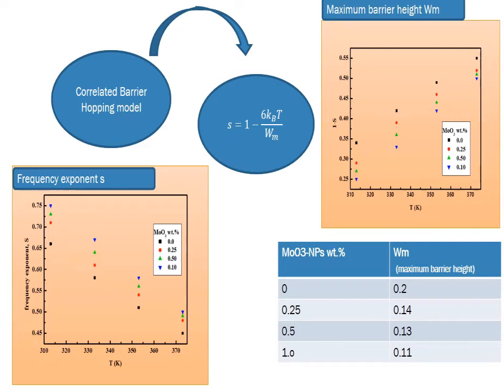The frequency exponent is drawn here as a function of temperature, and we observed that the frequency exponent decreases with increasing temperature for all our samples. This means that the correlated barrier hopping model is the dominant mechanism for the AC conduction, so we calculate the maximum barrier height from this equation by drawing a relation of 1 minus S as a function of temperature, and from the slope we get the maximum barrier height for the pure sample, zero concentration of molybdenum trioxide nanoparticles, and all concentrations of molybdenum trioxide nanoparticles. We observed that the maximum barrier height slightly decreases with increase in molybdenum trioxide nanoparticle concentration.